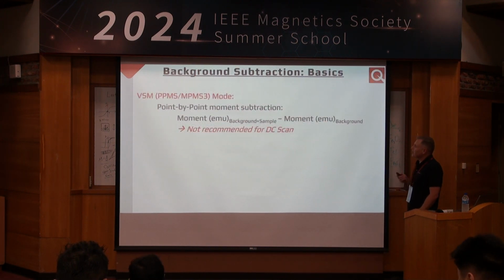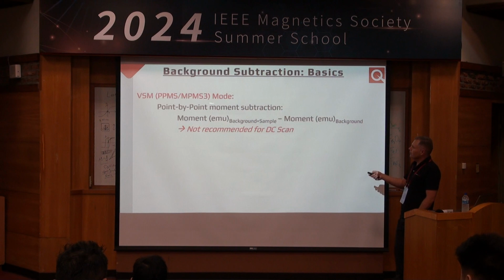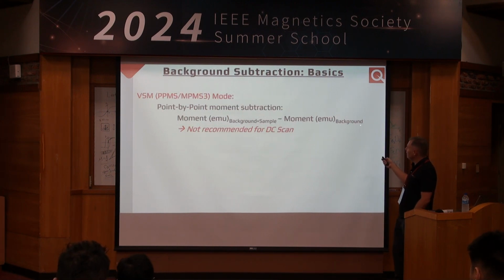So background subtraction, the basics. For VSM, the MPMS3, if you're doing the SQUID VSM mode, a point-by-point subtraction is pretty much all you need. You want to have the moment of your background plus the sample, and you just subtract off the moment of your background. Ideally, you want to have whatever sample holder you have, the only difference between these two measurements is the sample. And usually you can get away with this.